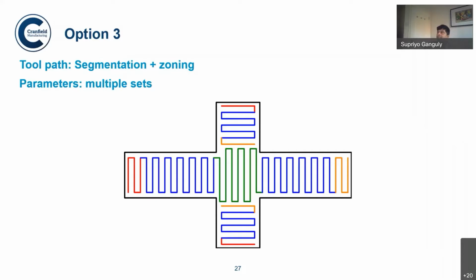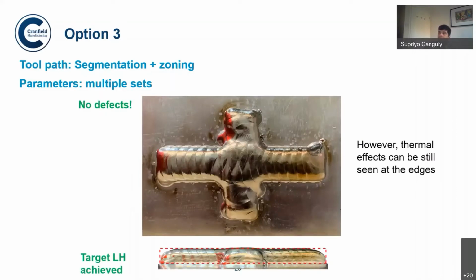And here it is showing, as you can see, that there is segmentation and zoning in the toolpath. So the different colors are showing that the speeds and so on are changing, and multiple sets of parameters are used. So once this was done, it managed to create a completely sound cruciform, with target layer height in every aspect of the deposit. However, the thermal effects can still be seen at the edges, which you can see here.